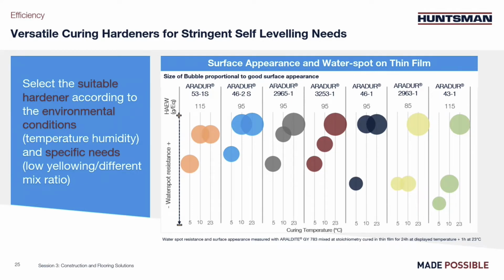On the other hand, if the product used will be in a warm area, the choice might be about having a long open time more than curing at 5 degrees. So in that case, Aradur 2963-1 works very well, as it is not too fast, it's low viscosity, and has still a very good appearance at room temperature. Generally, in this subject, there might be other needs, like mix ratio or being low yellowing. And at the end, it's all about optimization and priority, I would say.